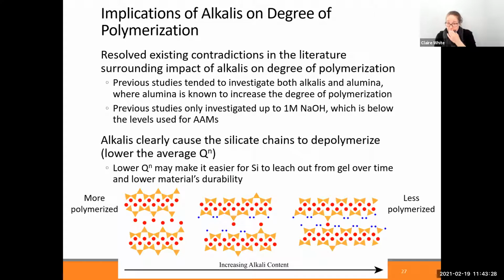And so the reason for this idea, well, let me go to the second part here first. It's clear that the alkalis cause the silicate chains to depolymerize, so you get a lower QN value. Now, it's not directly shown, but you can think about the fact that if you have a lower QN value, it may make it easier for silicates to leach out from the gel over time because they're not as strongly bonded into the system, in contrast to, say, a highly coordinated Q4 type arrangement of the silicates.